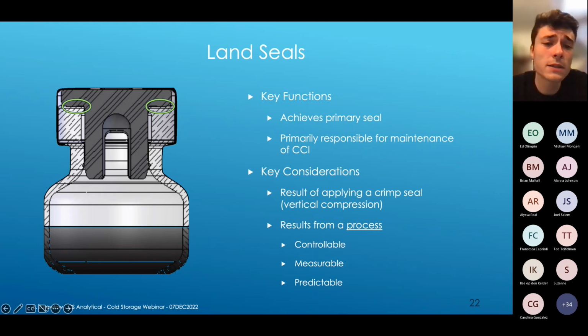The land seals, however, this is where we typically achieve a primary seal for vial package systems. This is really the seal that's responsible for maintaining CCI through the shelf life of that product system. Some key considerations here is that the land seal and the quality of this land seal is really a result of the crimping process. So instead of being innate to those package components and just a function of how those components fit together, here a very critical parameter that's going to lead to a good land seal is going to be the process by which that seal is applied. And because it is a process that's yielding this seal, then we know that it can be controlled, it can be measured, and to a certain extent, it can be predictable.